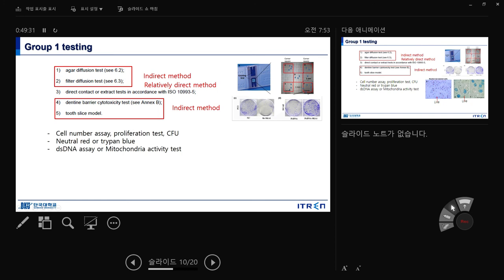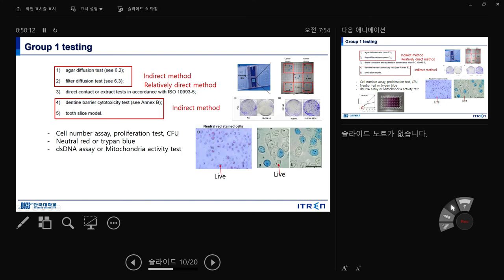Nowadays, mitochondrial activity tests are commonly used: CCK, MTT, MTS, or live/dead staining. I always tell you not to rely only on CCK — it only checks cell viability based on mitochondria activity. If your material decreases mitochondrial activity without causing actual cell death, the MTT assay will show decreased 'cell viability,' but this is really decreased mitochondrial activity, not true cell death. Live/dead staining is more accurate. Use CCK or MTS supplementarily to indicate mitochondrial activity, and mention it as such.